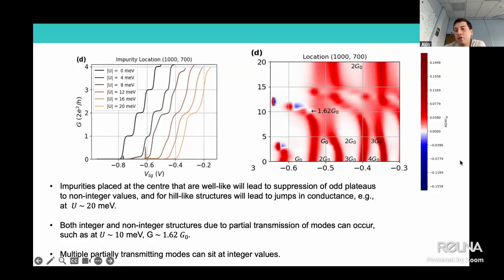And in the transconductance plot, you can also see this in the higher region. So you have the first plateau, you have a riser, then you have a plateau again, but this plateau is at 4e squared over h. So two of the spin degenerate modes that we have in the system. What I talked about with this 4 milli-electron volt trace is also shown here. So here in the zero impurity case, we have our riser, then a plateau, riser, plateau, riser, plateau structure.